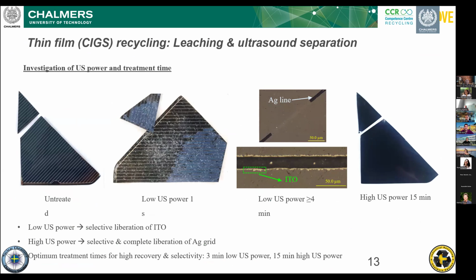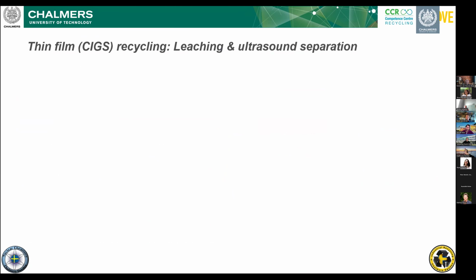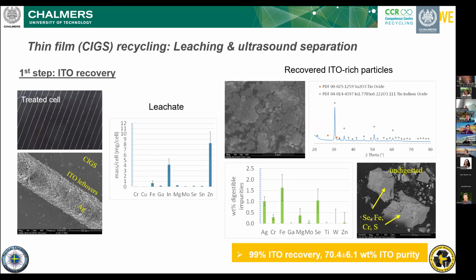But as you can see, when we are working in between, we realize that there is still some ITO left over around the silver lines. So we focus on a bit of optimization of that process. In the first step, we leach the window layer, which is the main zinc-rich layer, and we only have a really small amount of indium loss in the initial leaching. Then we can recover the ITO layer as ITO-rich particles with a minimum amount of impurities. ITO recovery reaches 99%, and purity is directly 70% in a one-step recycling method. That gives us a really good base to increase its purity.